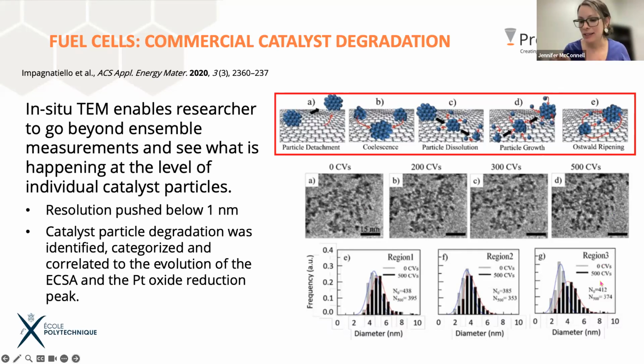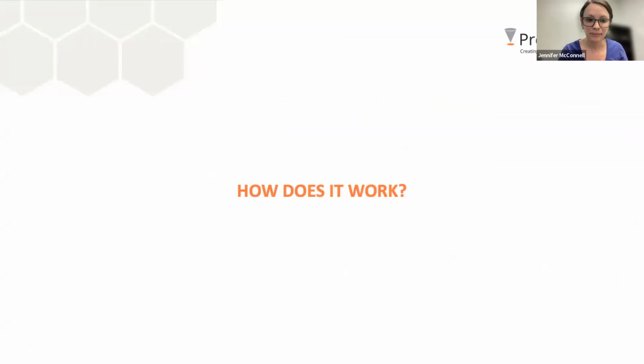This was really interesting because in liquid, for those of you that have a lot of microscopy experience, you can probably imagine imaging in liquid, it's not an atomic resolution technique. And so that is just an expectation you should go ahead and put in your brain. You're probably not going to get atomic resolution in liquid, but to be able to analyze 3 nanometer particles and push the resolution down to 1 nanometer. We've got as much equipment and chips and variations as possible to try and help you minimize scatter from the liquids, so that you can get the best resolution that you can without potentially damaging your sample from dose or creating radiolysis products and such like that. So really cool, interesting examples.